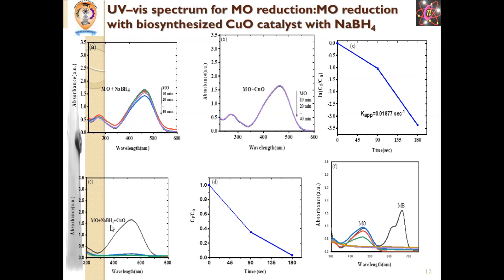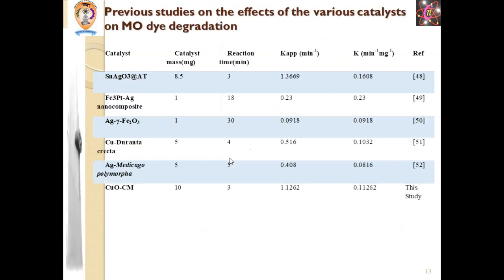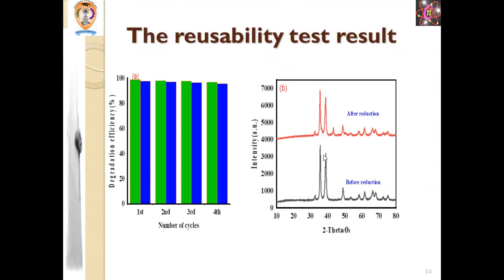So you can observe that our material effectively degrades the organic dye, and it is suggested that industries and academia can adopt this approach and make it in a large scale for further treatment of industrial effluents to make a green environment. Our result was summarized in this table. Again, these results are very important, and we found them highly appreciated results with enhanced catalytic properties of our material compared to the previous literature.